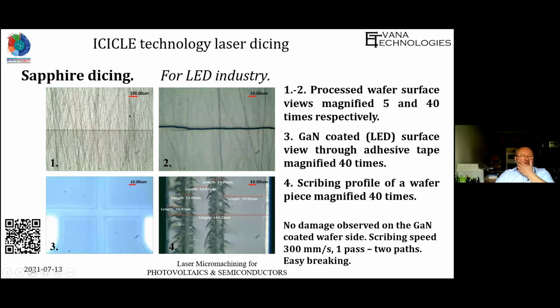Here you can see another material, sapphire dicing. This is mainly dedicated to the LED industry, and again after scribing you can see a cracking line on the surface. Here you already can see cracking, and the line sometimes is quite smooth, sometimes not very smooth, but anyway in the range of plus or minus 10 micrometers you can easily fit into the street of the LED wafer.